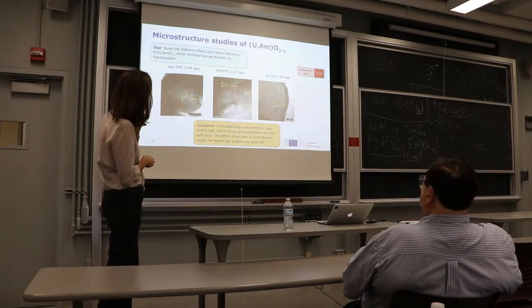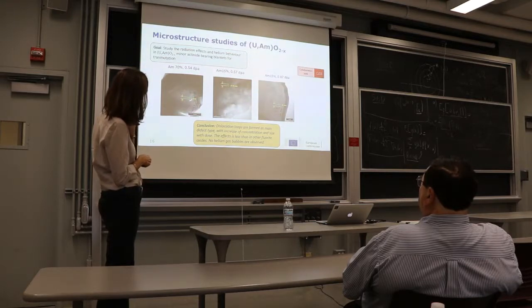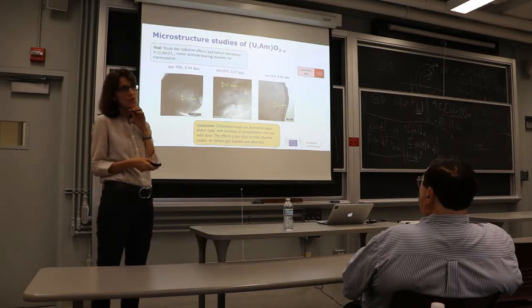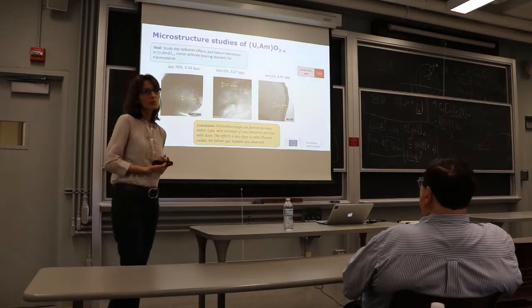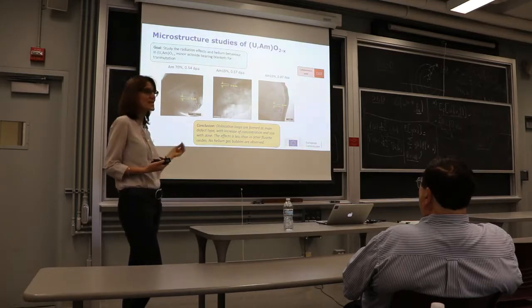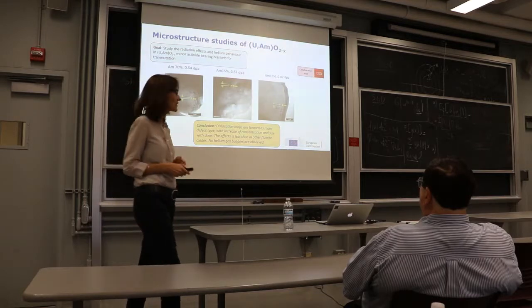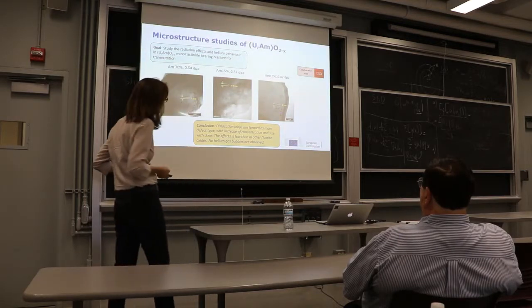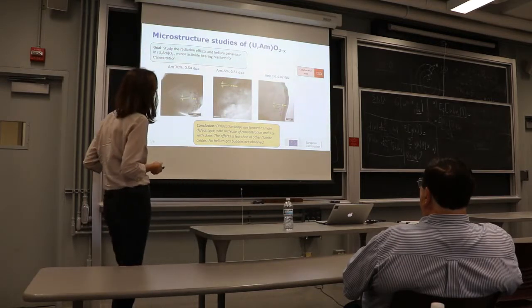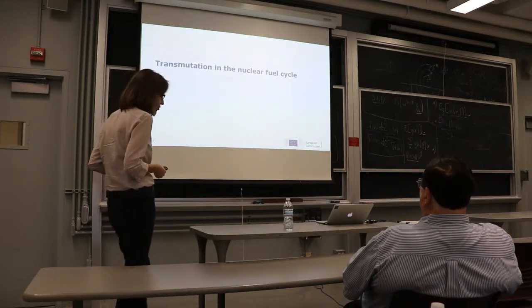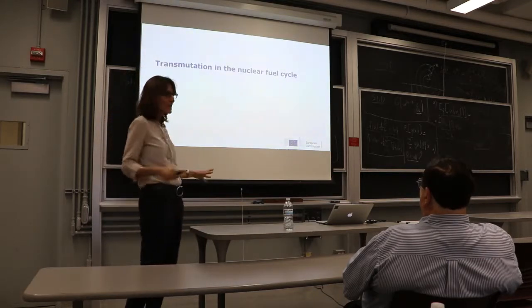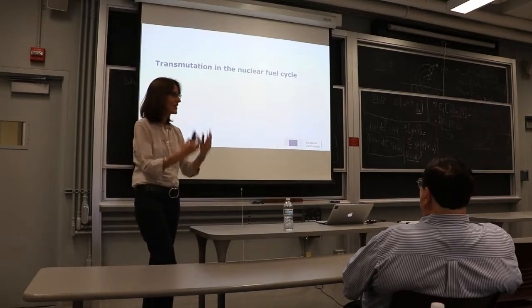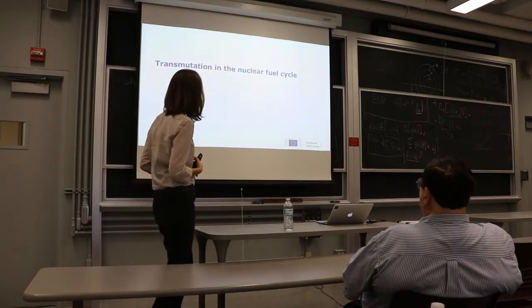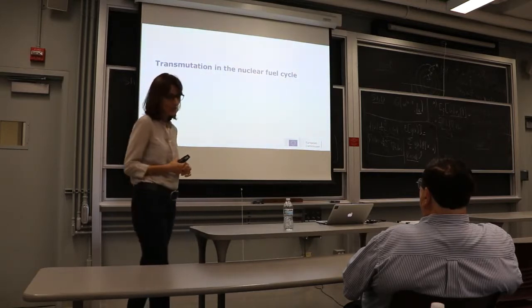And you see, we can measure the loops at nanometer level with the TEM. So, and the uniqueness of this is that we can do it on irradiated material, and that's not done everywhere. So irradiated fuels is not easy to do it everywhere. Okay, so this was the last slide concerning the introduction to the JRC and to Europe.